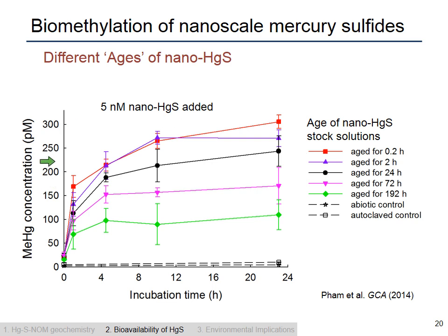And so what we can see here is methylmercury produced as a function of incubation time for the different aging states of nanoparticles. And you can see that the youngest particles, the ones that are freshly precipitated, have the greatest methylation potential. We see the most amount of methylmercury produced by those organisms that get the youngest nanoparticles. And then with age of the nanoparticles, we see a decrease in its methylation potential.